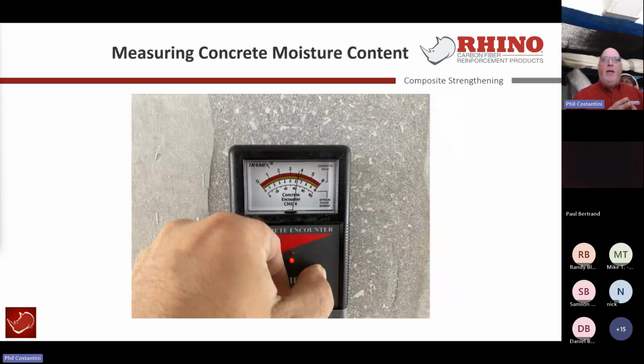Now here's a critical one. And again, these are governing things that we add to our quality control and quality assurance. Moisture in the concrete, especially for those of you that are working in even potentially a residential home that's a heritage home or a home that's been built 100 years ago or 50 years ago, and it's got high levels of relative humidity and moisture in the basement. Make sure you have a moisture meter on you, and don't moisture meter the surface of the concrete that you didn't prep. Moisture meter the surface of the concrete that you prepped.